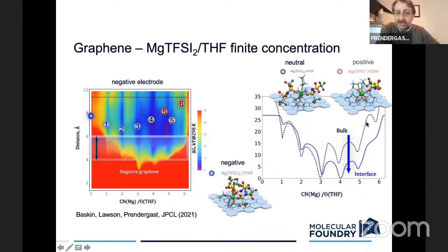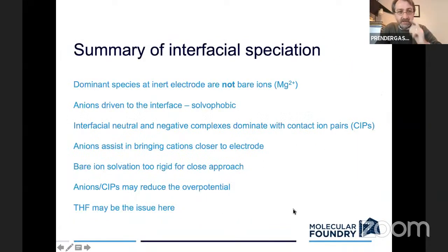Not the bare ion. There isn't enough energy in the charging of the system to break apart the solvation environment around the fully coordinated cation with just the solvent. And so that remains a minority species. So that's pretty surprising. This just came out in JPCL in the last month or so. And so it begins to explain a lot about what the dominant species might be at the interface. It's not just the bare ions, even though you might think so simplistically.